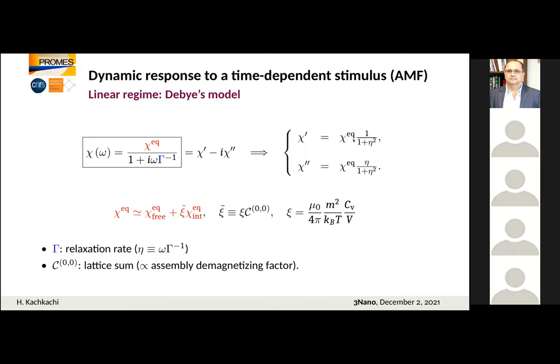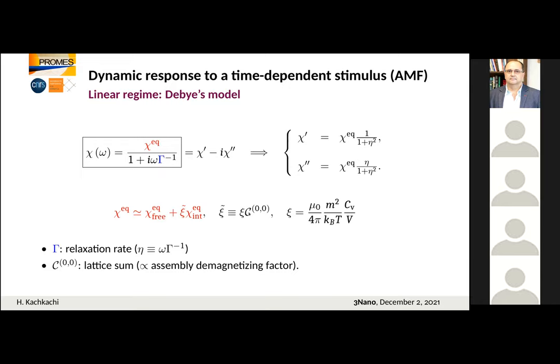But now, if you apply this to an assembly of nanoparticles, you know that nanoparticles are actually interacting. So you need to take into account interactions and also the relaxation time, because you have to compute this gamma, the relaxation rate of the magnetization. These two quantities are rather complicated. Eta here is omega multiplied by the relaxation time, some reduced frequency. Another very important parameter related to the assembly properties is the lattice sum C00, the first of a hierarchy of lattice sums. It tells us whether the assembly is prolate or oblate, and what its spatial organization is.